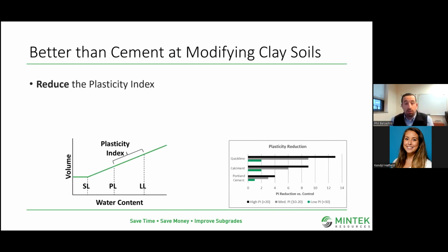So there is no rule of thumb of how much material to put in to reduce PI. You'll go crazy trying to correlate it. Believe me, we've tried in the lab. You really need that lab testing to determine exactly the benefit that you can see. And that's an example of what we're seeing here in this chart. We compared the performance of lime to Portland cement with a low, medium, and high plasticity soil. You can see that quicklime really dropped the gap the most. It was the best at modifying those troublesome soils with the high plasticity index.